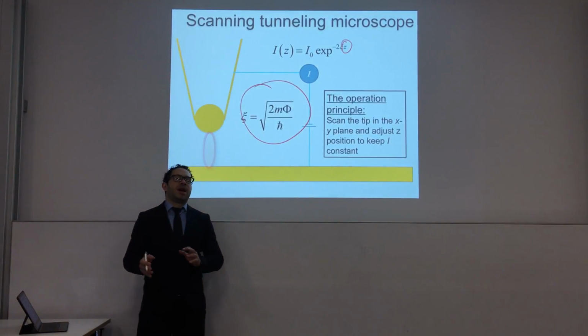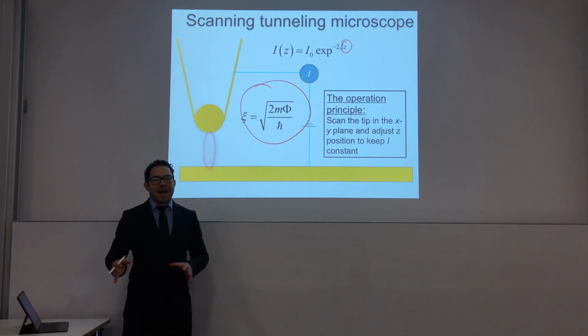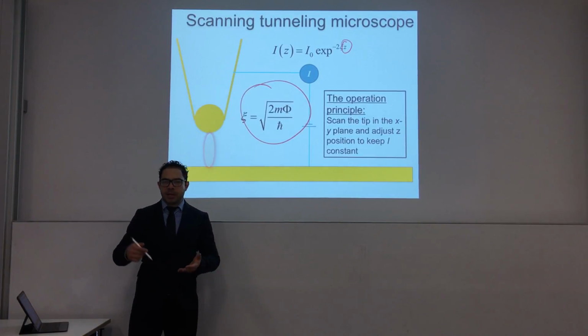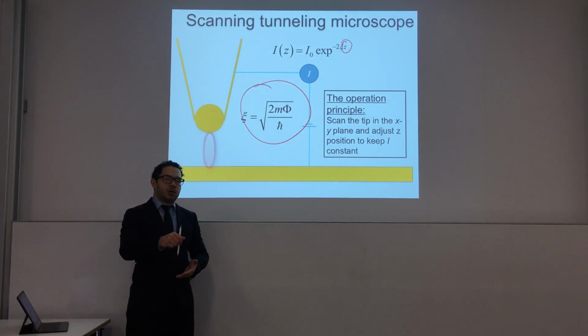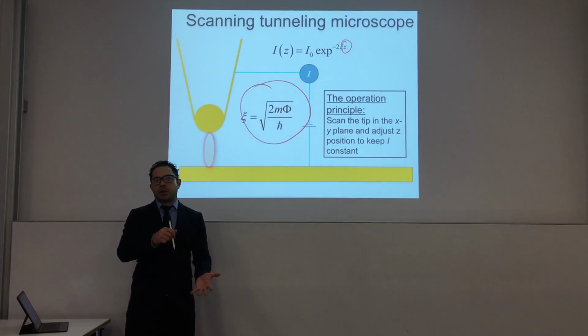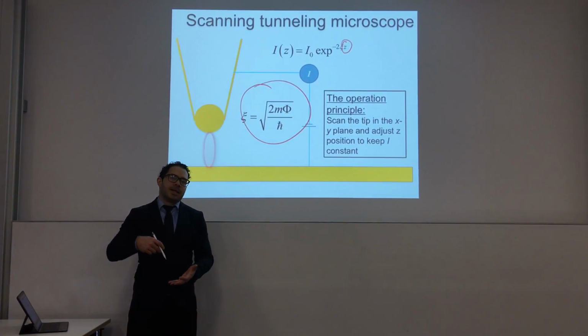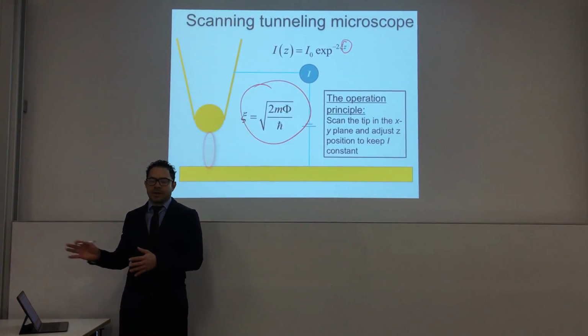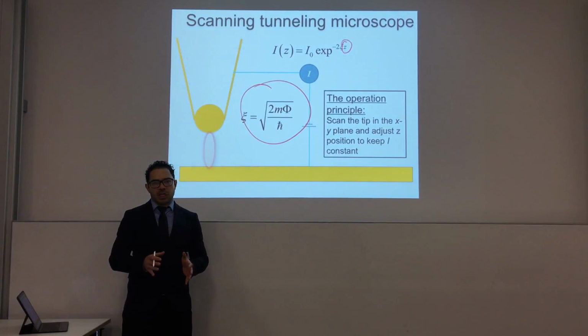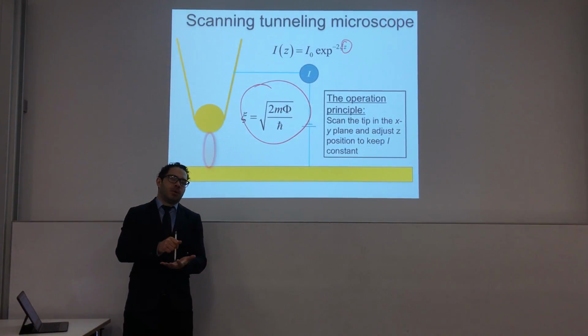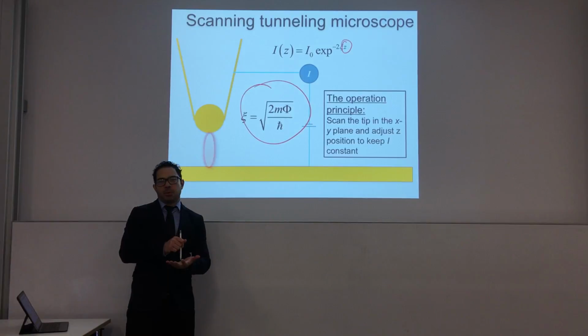So let's consider if you have some vacancies, some atoms missing in your surface. Then when the tip goes to that region, there are some missing atoms, so the current will decrease because there's nothing there. Then the STM electronics will react to this change by approaching the tip to the sample even more.